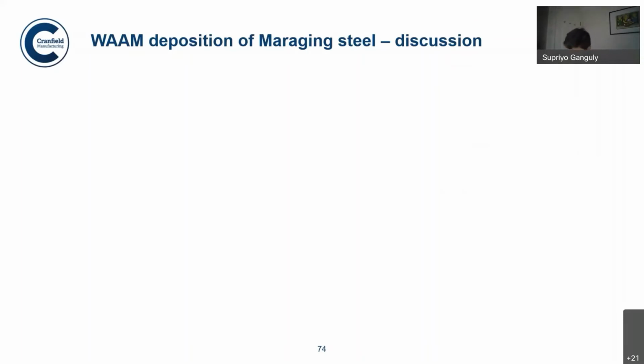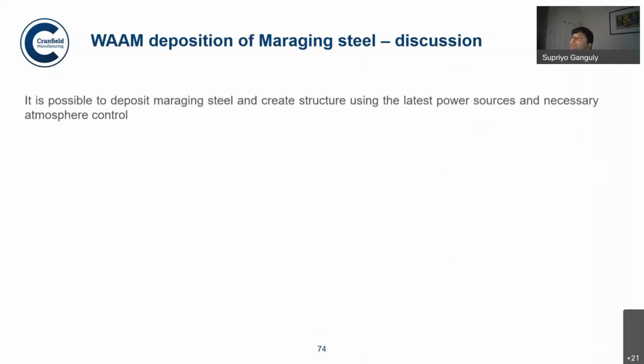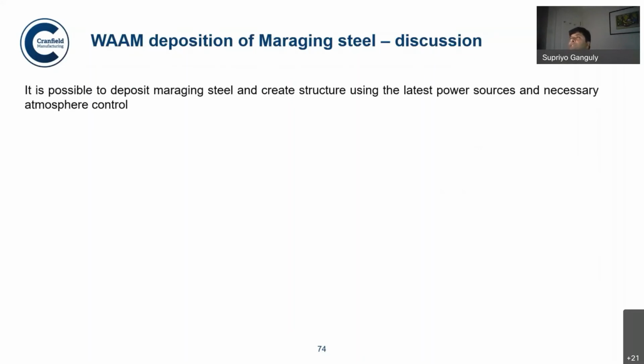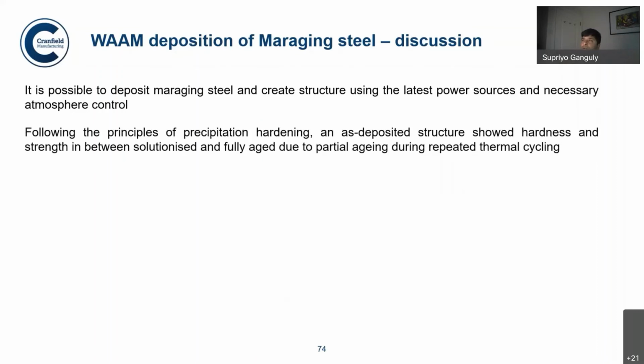Okay, so that brings me almost to the end of the presentation. This work is quite significant towards the development of CoE-WAAM as a very important tool for manufacturing of high-end alloys. So it is possible to deposit and create structure using the latest power sources and necessary atmosphere control. Following the principles of precipitation hardening, the as-deposited structure showed hardness and strength in between, as I was just saying. So you can age the as-deposited structure, but you never achieve the maximum strength that you can achieve using rolling.